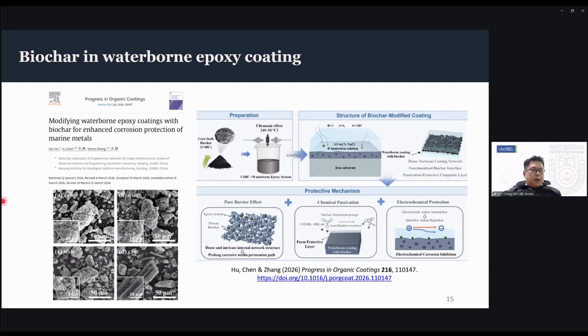Other things they played around with in this study included sonication. They found that if they sonicate at a higher temperature, it improved the dispersion of the biochar inside the organic matrix, which helps minimize agglomeration and promotes the formation of a denser and more uniform coating structure. So that's roughly most of the background I wanted to talk about.